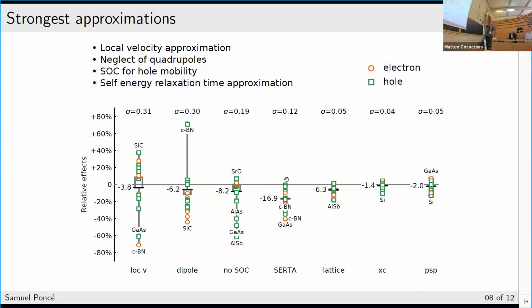If you neglect spin-orbit coupling, that's also very interesting. Spin-orbit coupling will typically not modify the conduction band, at least for the simple III-V semiconductors, but it will change the valence band. You get spin-orbit splitting of the degenerate manifold, and that has a big impact. Even in silicon, where you only have 43 meV splitting, that has an impact because what matters for transport is really the edge, maybe the 0.1 to 0.2 eV near the valence band maximum. So changing your bands there has a big effect. You can see very big underestimation, and all the ones that change a lot are the hole mobilities, never the electron. So spin-orbit coupling is important for the hole mobility.